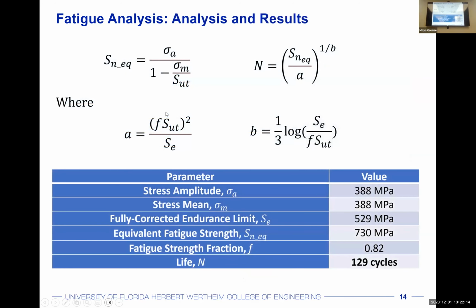All right, so to go through the analysis itself, the amplitude and mean stress were calculated based on that maximum stress on the previous slide and a minimum stress just assuming 0 with no impact. The fully corrected endurance limit and a fatigue strength factor were taken into account as well for our material and our geometry. And then an equivalent fatigue strength was calculated using that amplitude as well as the ultimate strength of the material and was calculated following the Goodman relationship.